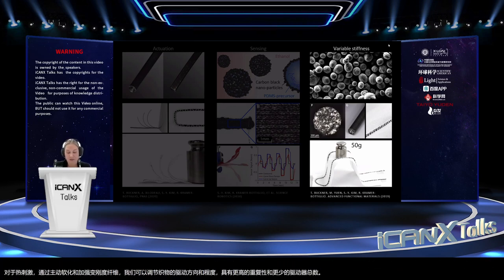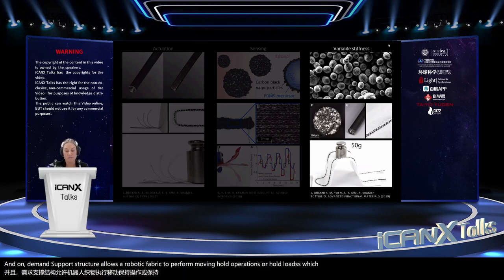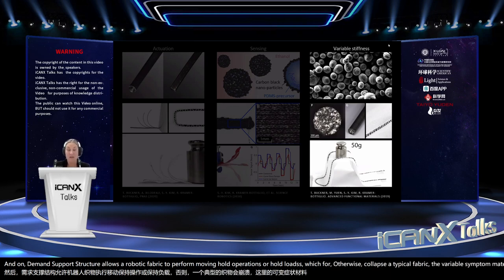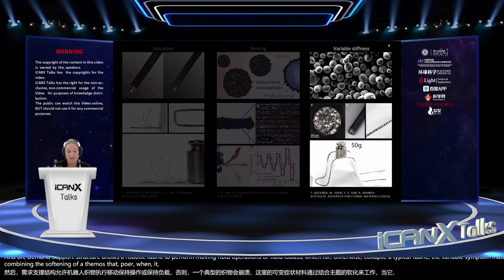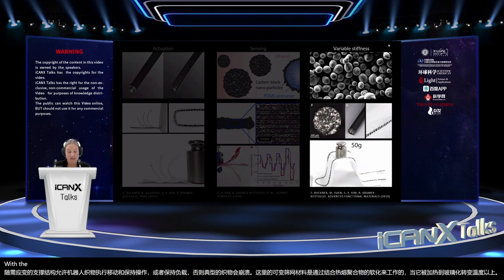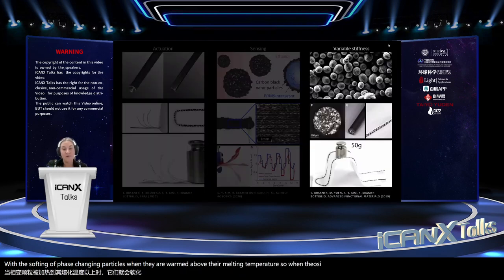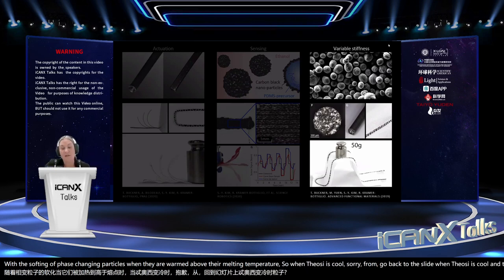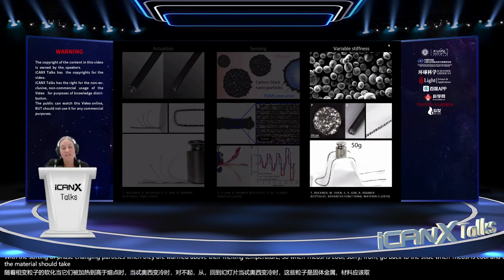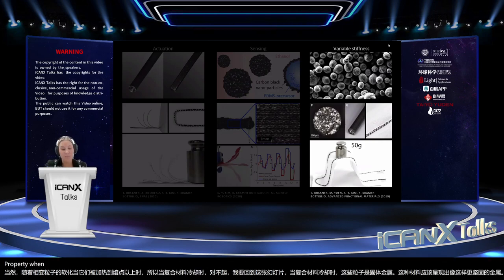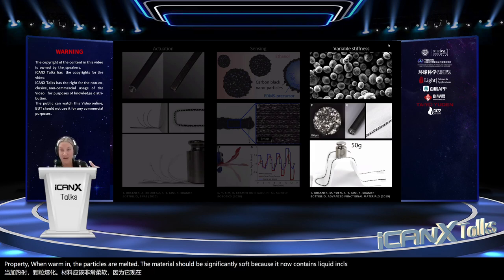An on-demand support structure allows a robotic fabric to perform move and hold operations or hold loads which would otherwise collapse a typical fabric. The variable stiffness material here works by combining the softening of a thermoset polymer when it's warmed above its glass transition temperature with the softening of phase-changing particles when they are warmed above their melting temperature. So when the composite is cool and the particles are solid metal, the material should take on more solid metal-like properties. When warm and the particles are melted, the material should be significantly softer because it now contains liquid inclusions rather than solid inclusions.